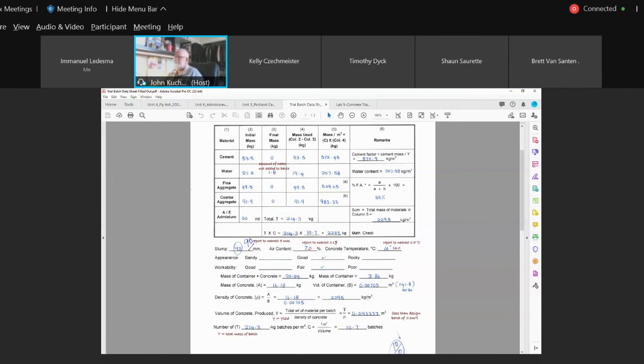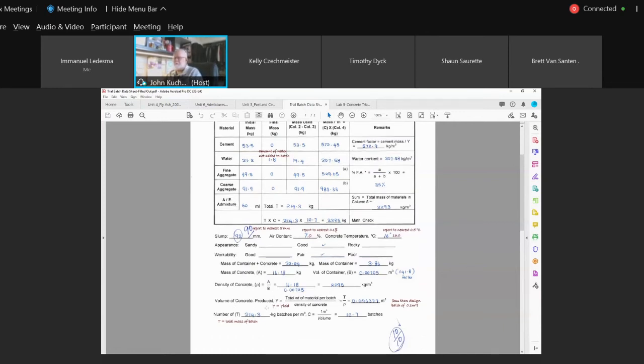Straightforward. Now here's a clincher: remember I said you want to design for 1 cubic meter, but from a ready-mix producer's point of view, you want to make sure you don't shortchange your customers. So typically when designing, I'll design a little bit more than 1 cubic meter. This is why—if you look at the volume of concrete produced, it's called yield. What volume do these proportions yield? Did it yield 1 cubic meter of concrete? We can base that on the density test. That's why density testing on concrete is very important.